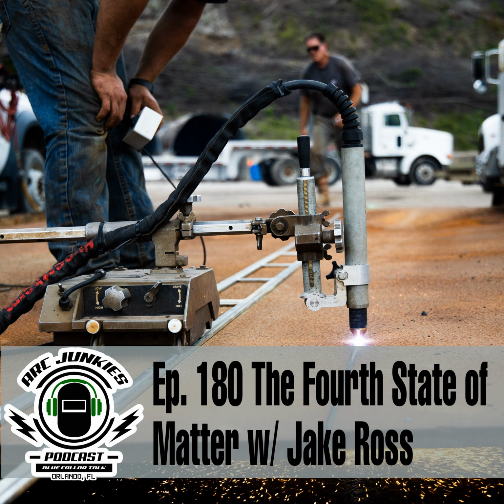Oh, yeah. And you're left with around 3/16 of an inch that you would grind down. But the other thing is after you do that initial cut, you just tilt the torch up a little bit and you can do a plasma washing process. Okay. And you can get it very, very close without damaging the base material. So that comes down to grinding less. Everybody wants to grind less, abrasives cost as well.